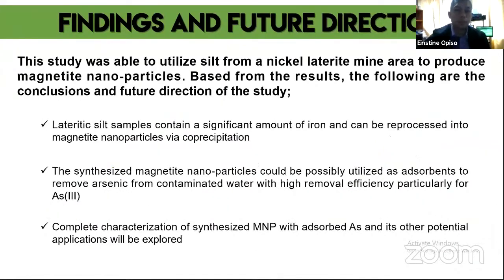So for our major findings and future directions, as this project is still ongoing, based on our results, the study was able to utilize silt from a nickel laterite mine area to produce magnetite nanoparticles. The lateritic silt samples that we obtained contain a significant amount of iron and can be reprocessed into magnetite nanoparticles via co-precipitation. Then the synthesized magnetite nanoparticles could possibly be utilized as adsorbents to remove arsenic from contaminated water with high removal efficiency, particularly for arsenite.